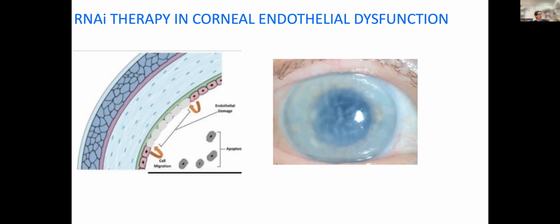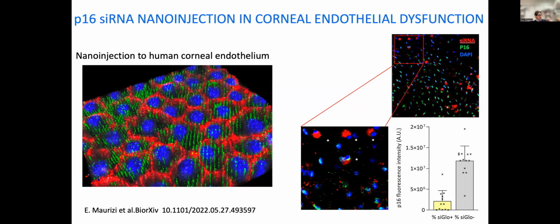So the idea is that if you can regenerate these cells, if you can stimulate these cells that are still there to reproduce and to divide, then you can reestablish the endothelium and control water ingress. And so what we did is that we loaded our needles with an siRNA that targets P16, and P16 is an inhibitor of cell division.